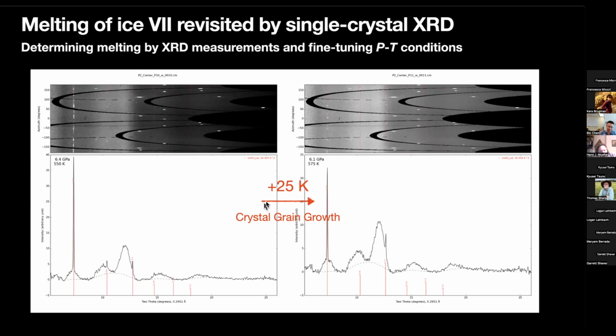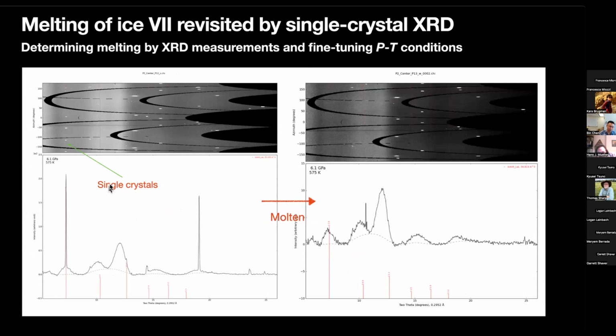But by just increasing 25 Kelvin, you can see the ice becomes more single crystal. And then after a while, we stay there for a little bit of time, and even at the same temperature, we see the disappearance of the single crystal peaks for ice. So that means the melting temperature is very close to 575 Kelvin at 6.1 GPa.